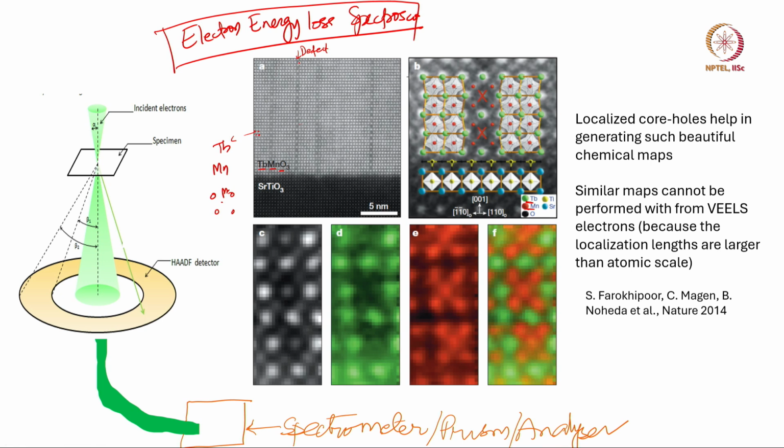you see some other contrast, right. So, how do I know that this atom that I am seeing is really terbium? I can do this spectroscopy and then I can actually image all these green things, right. So, this is the signal coming from terbium atoms, right. So, I can say that this atom is actually terbium.